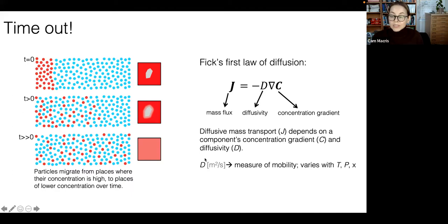This behavior is dictated by Fick's first law of diffusion, which states that diffusing mass transport depends on the component's concentration gradients, here, del C, and its diffusivity or diffusion coefficient, this D here. The diffusivity or diffusion coefficient is a measure of the mobility of a component, and it will vary with temperature, pressure, and composition.